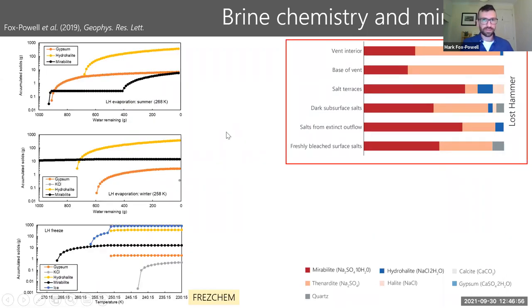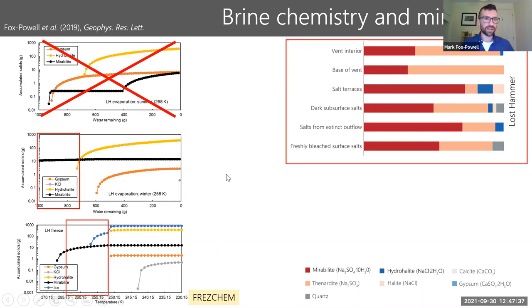So again, we did a bit of thermodynamic modeling to try and understand how this deposit forms. This is the same program I used in the first part of the talk, FREZCHEM. Here you just see the system solidifying under three different conditions. We have evaporation occurring under both summer Arctic temperatures and winter Arctic temperatures, and freezing in the lower panel. The first thing to notice is that summer evaporation forms a lot of gypsum, and we don't see any gypsum in this deposit. So that rules out the warmer evaporative mechanism to form this deposit. This is a cold temperature deposit. It's forming under winter conditions.